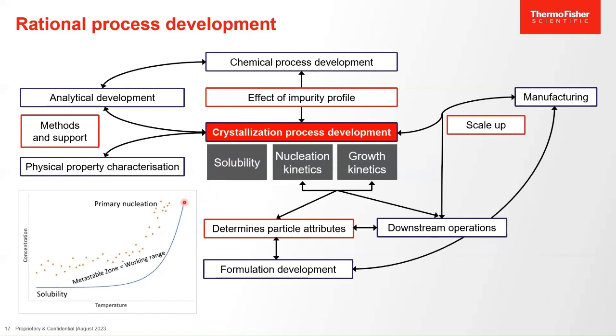The solubility determines the type of process that you will select. It determines the lower working range for your crystallization process, and it also determines the maximum yield that you can expect from your process. Your starting concentration may be somewhere up here. Your final concentration may be down here, and the difference between these 2 concentrations is the maximum yield you can expect from your process. Nucleation kinetics and growth kinetics are the 2 other important factors.